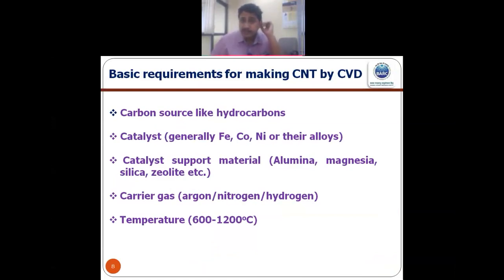Now, when we want to make the carbon nanotube using chemical vapor deposition, which can actually give you a large scale synthesis of carbon nanotube, you require a carbon source like hydrocarbon, a catalyst, generally transition metals or their alloys, then catalyst support material, because these catalysts are in nano form and we need to disperse them, otherwise they will agglomerate. So for the dispersion we require a support material, generally alumina, magnesia, silica, zeolite, etc. A carrier gas for dilution of the hydrocarbon, like argon, hydrogen, nitrogen, or their mixture, is used, and temperature is required to give the activation energy for the growth of the carbon nanotube.